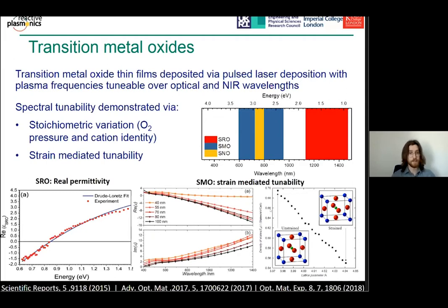And this spectral tunability in the screened plasma frequency was possible due to changing the cation in the B site. So if, for example, we move from SRO, strontium ruthenate, to strontium molybdate, we can shift the wavelength of operation. We can also have fine control by controlling the oxygen pressure in the deposition process and changing the oxygen stoichiometry. In these oxide films, we also identified strain-mediated tunability. So by changing the thickness of the film and introducing strain, or by changing the substrate, we can shift the charge carrier concentration and again change the wavelength at which we can operate. So that's useful if we're looking to translate this into plasmonic devices.